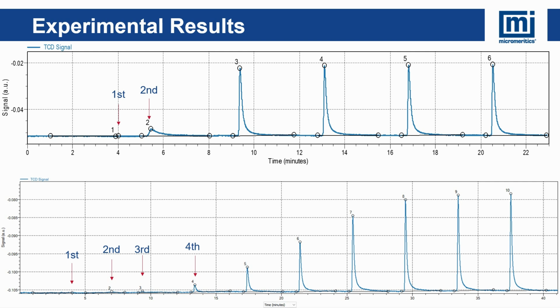The dispersion value obtained for the controlled process and the air-exposed sample were 29% and 105% respectively. The higher dispersion value in the second experiment highlights the susceptibility of the measurement to oxygen. First, oxygen can reoxidize the sample during the cleaning process. Second, hydrogen can react with oxygen, leading to a false positive result.